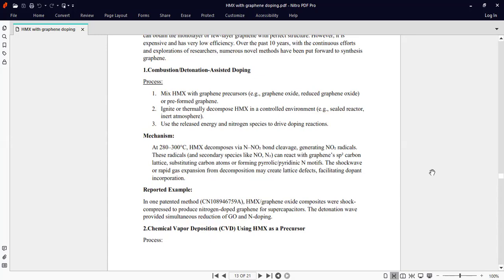HMX decomposes via N-NO2 bond cleavage, generating NO2 radicals. These radicals and secondary species like NO and N2 can react with the graphene sp2 carbon lattice, substituting carbon atoms or forming pyrrolic and pyridinic N motifs. The shock waves or rapid gas expansion from decomposition may create lattice defects, facilitating dopant incorporation.